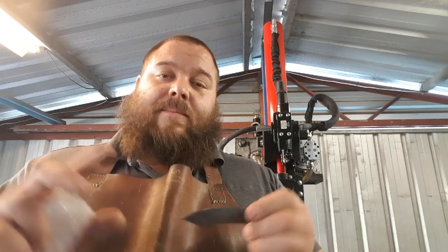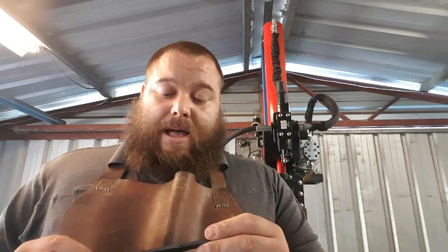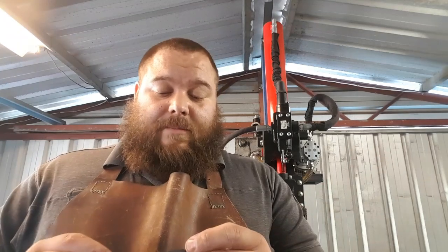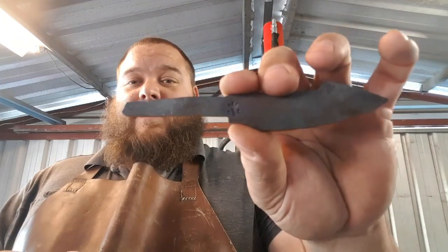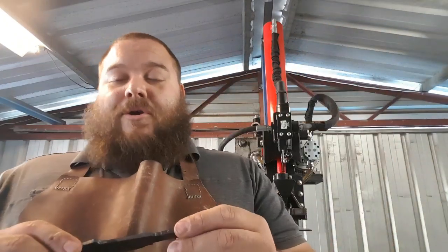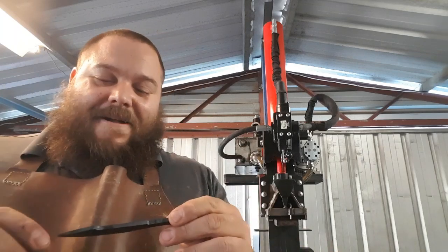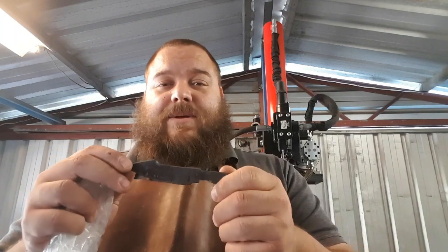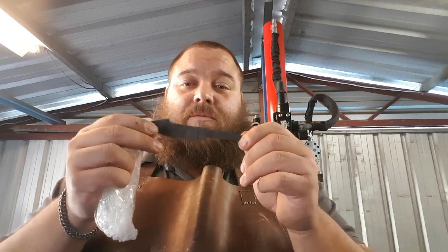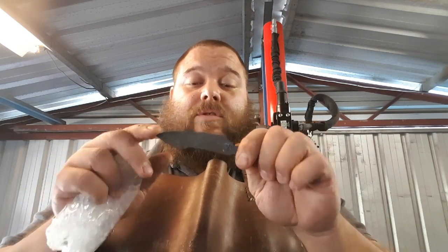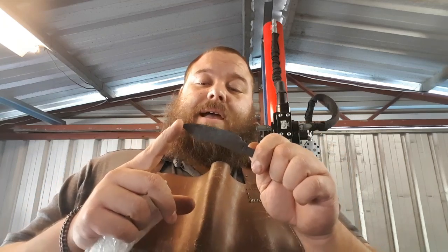He's left it quite chunky out of the forge so that I can play around with the geometry on the grinder, which is great because that means I have a little bit of control. And he has thrown his maker's mark in there, so we know where it came from. But all that needs to be done to this at this stage is to profile grind, just true up a few of the lines, and then do the bevels and flats, and she'll be ready to heat treat. So I'll show you the grinding process and then we'll get into how I do a Hamon.